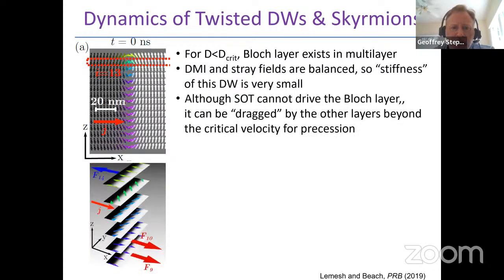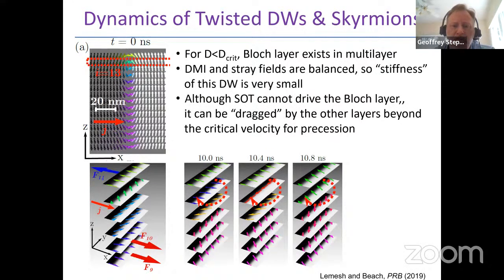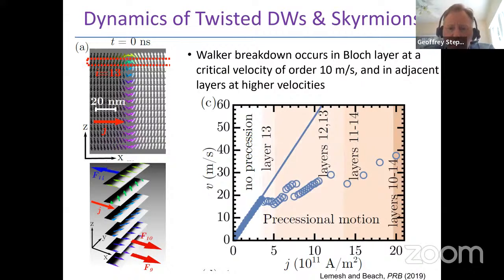That transition turns out to be at a much smaller velocity threshold for multilayers than it tends to be for continuous films. So as a domain wall or a skyrmion is traveling through a material, there's a critical velocity at which a layer will precess, and that critical velocity is proportional to the stiffness. So proportional to whatever is the energy term that is holding it as a Néel or holding it as a Bloch wall. And in magnetic multilayers, we've shown computationally that critical velocity can be very, very small. And again, because it is proportional to the stiffness of the domain wall, and that stiffness right at that node can be very, very low, then precession will tend to begin within a domain wall, within at least a few of these layers, at a very low velocity, and that will destabilize it.